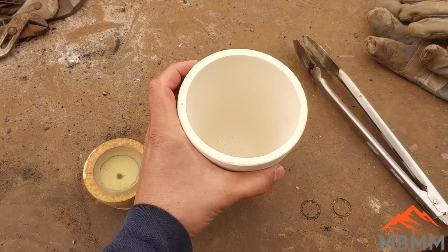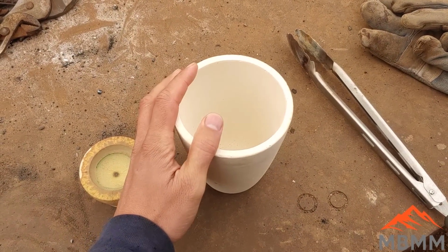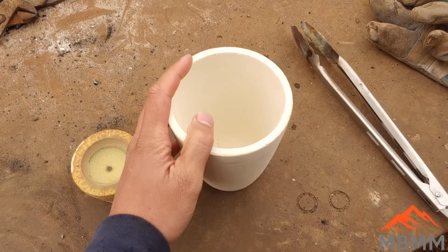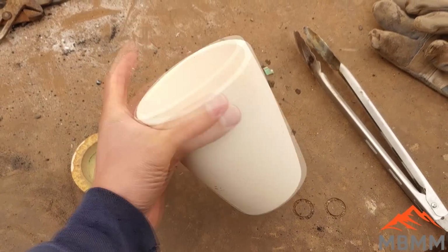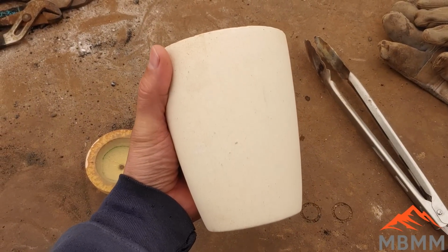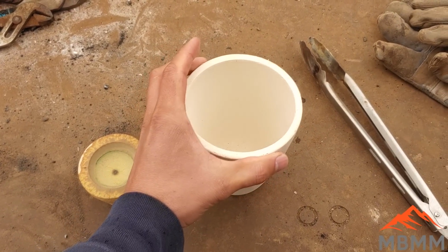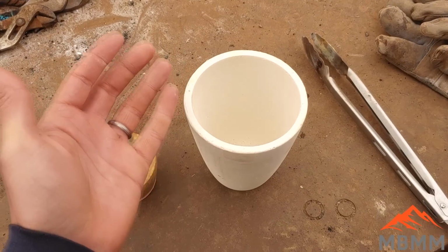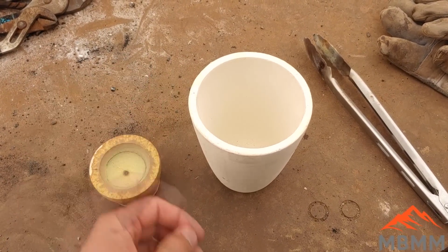And I'm not going to put any sulfides in it, but I'll put our 200 grams of anhydrous borax, 200 grams of lye, and 100 grams of silica, and see if the crucible fails just with the flux, or if it's that we're processing matte and it's essentially pure sulfide and it's just eating up the crucible.